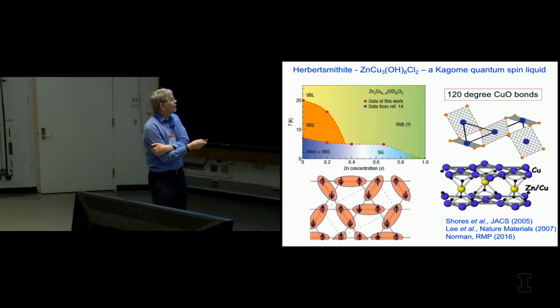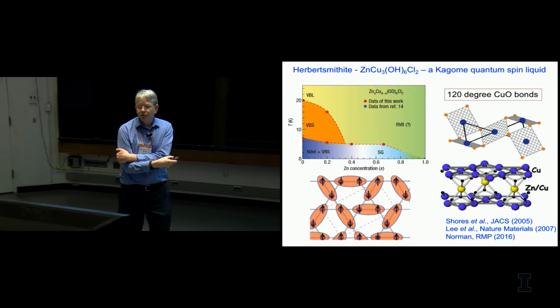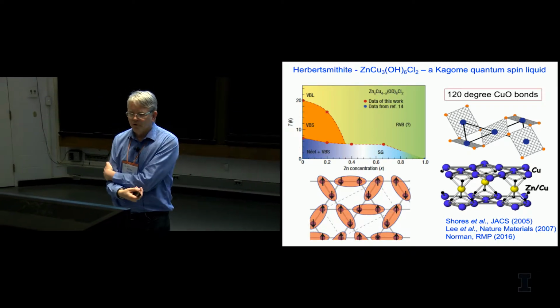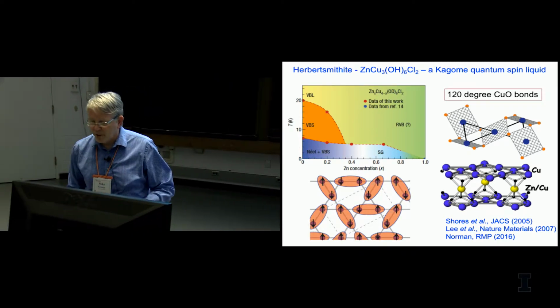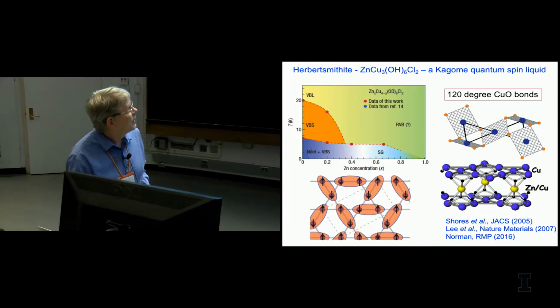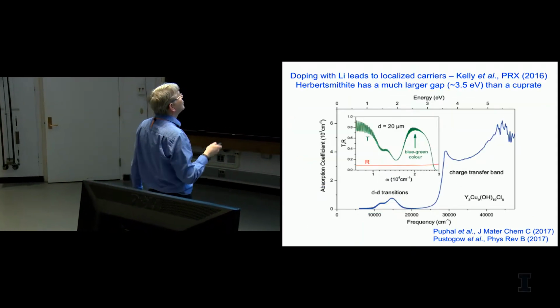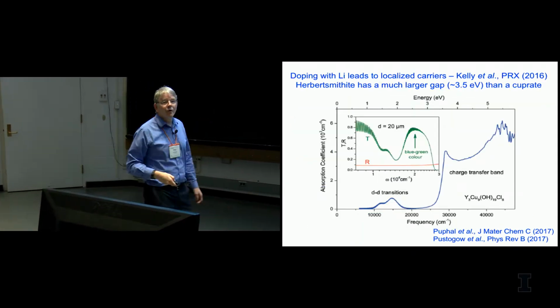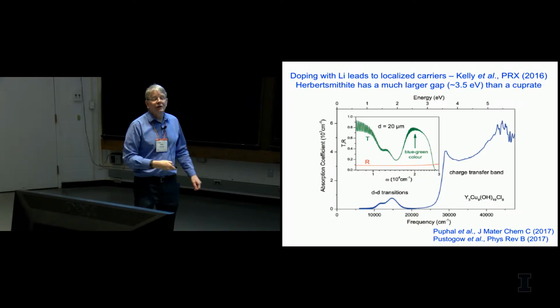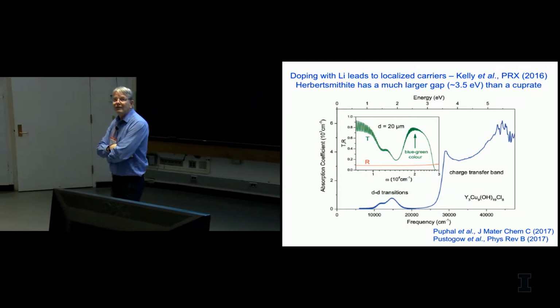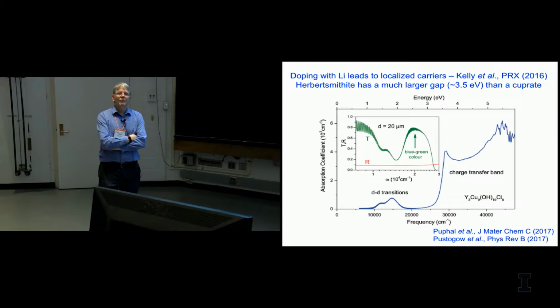And the proposal by Igor Mazin was that you would get an f-wave superconductor, sort of analogous to what Jim Sauls and I have proposed in the past for uranium platinum-3. The problem you run into in this case is that people have doped lithium into the material and you basically get nothing. The material remains insulating.